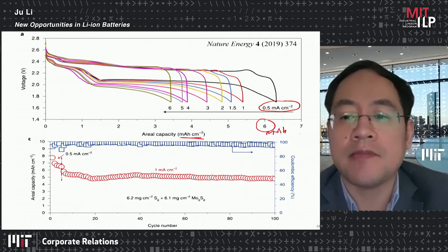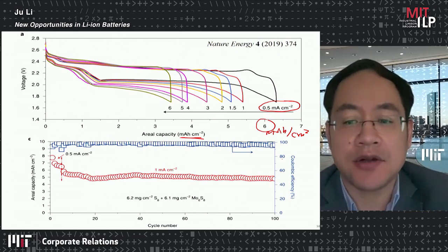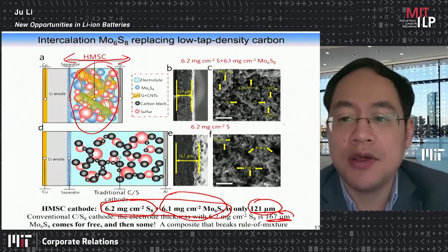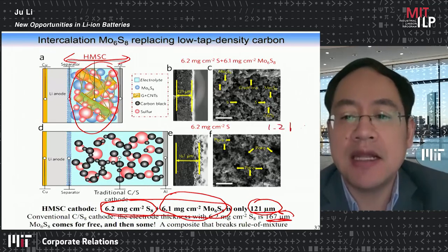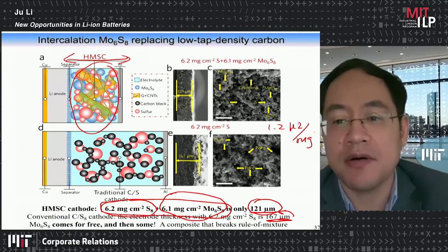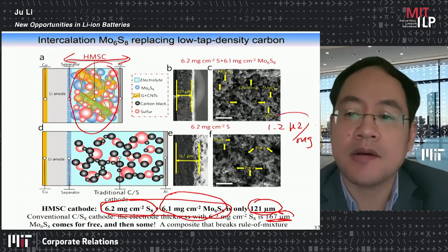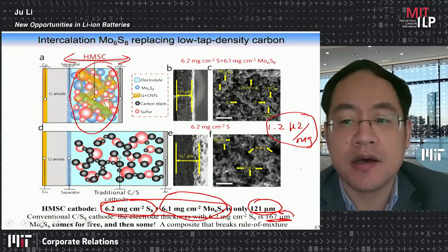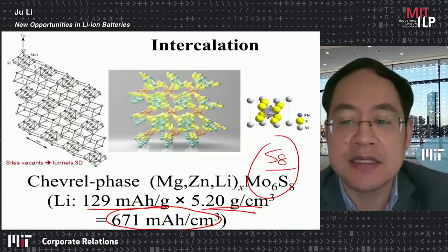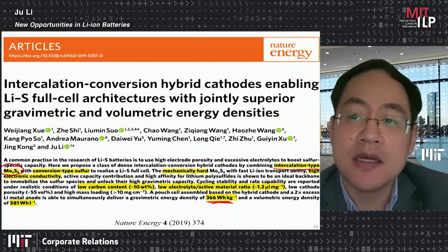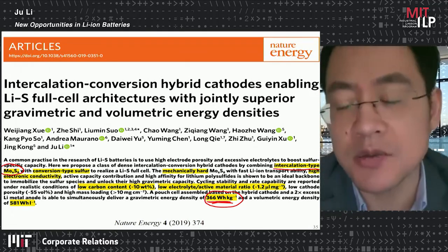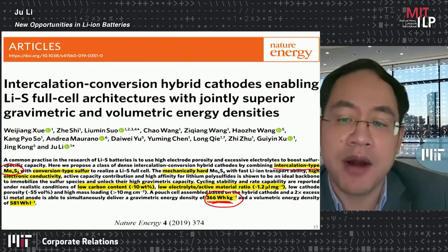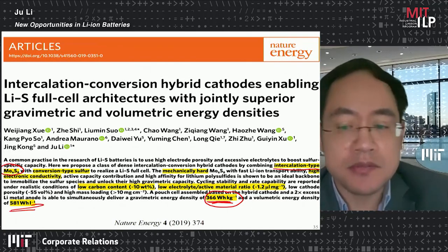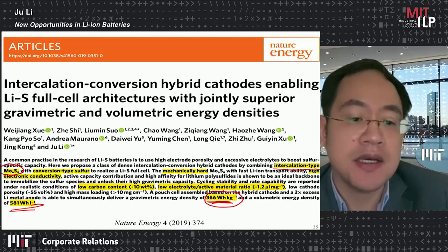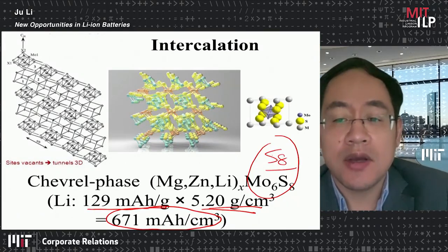And also we can use a very lean electrolyte. So in this case, we only use 1.2 microliter per milligram of cathode material. So we can end up with something like 360 watt hour per kilogram. And this is still using a very small pouch cell. So with a bigger pouch cell, we should be able to hit 400, but then a volumetric energy density which is close to 600 watt hour per liter.